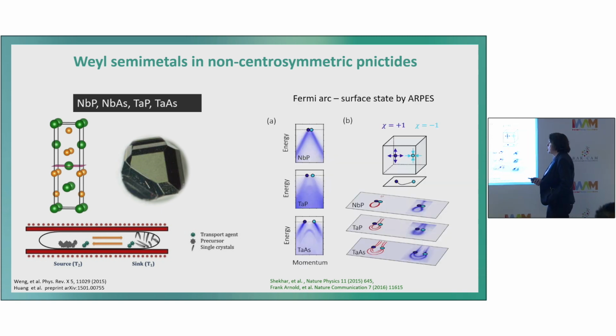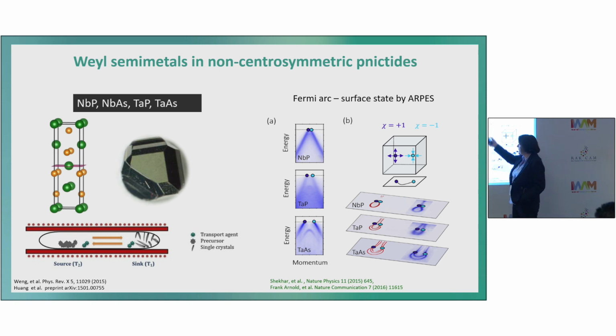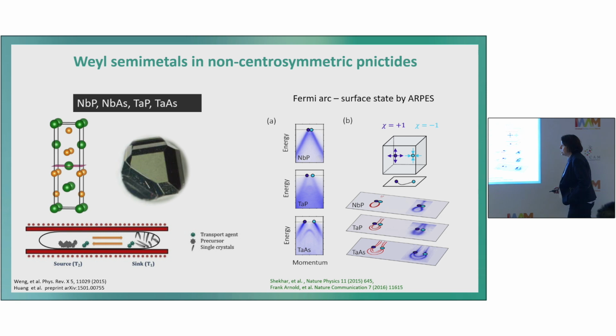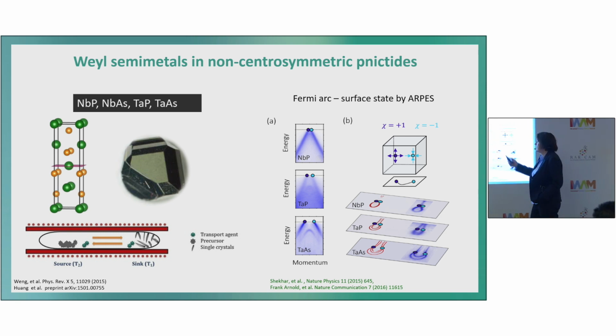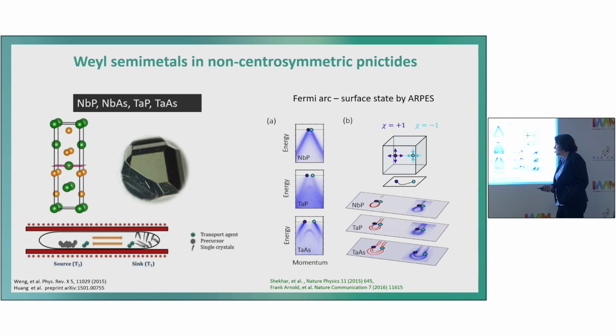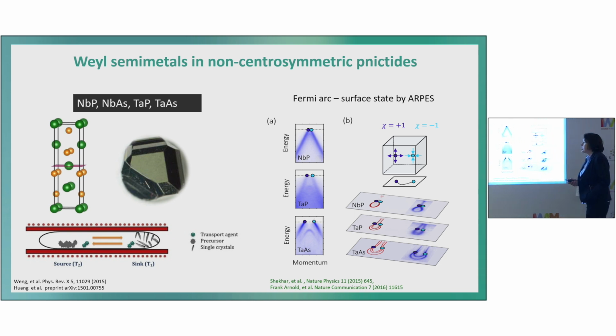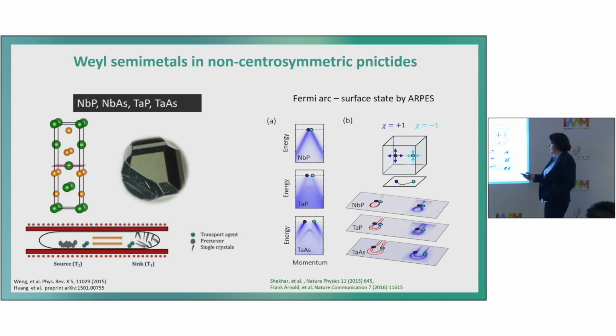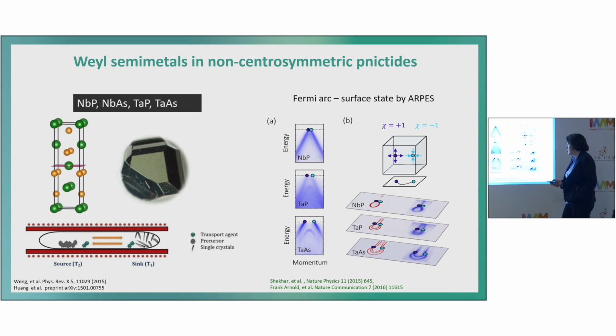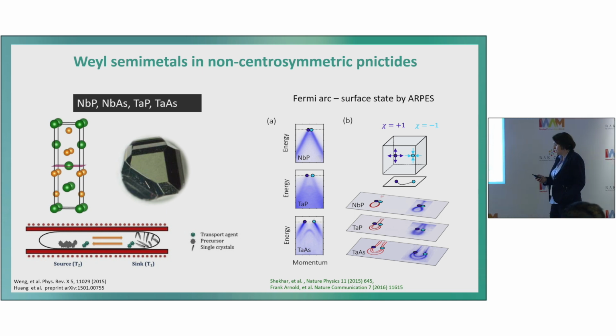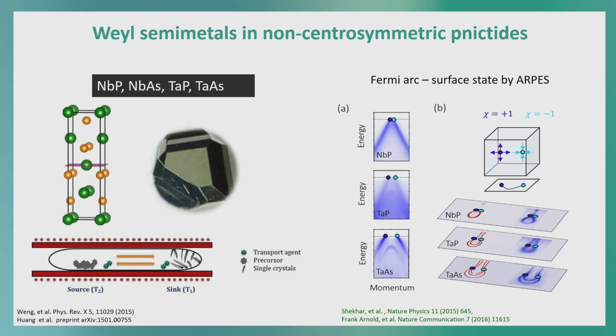And then the next step is to look whether we have Weyl points, and this we do by angle-resolved photoemission. This is looking for the linear dispersion of the bands, like in niobium phosphide, tantalum phosphide, and tantalum arsenide. We see even a band splitting, which is related to spin-orbit coupling. And if we make the elements of the materials heavier, we see a stronger splitting. Here are calculated Fermi arcs, but the Fermi arcs are quite tiny, so the distance is small in this material. And here we see the angle-resolved photoemission data connecting the Weyl points in the bulk on the surface via these Fermi arcs.